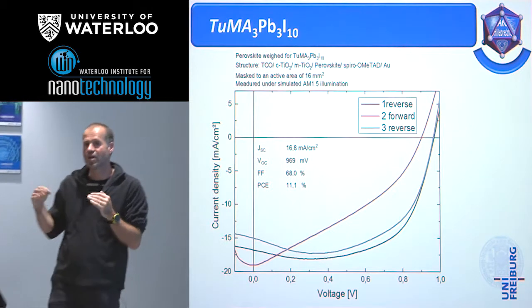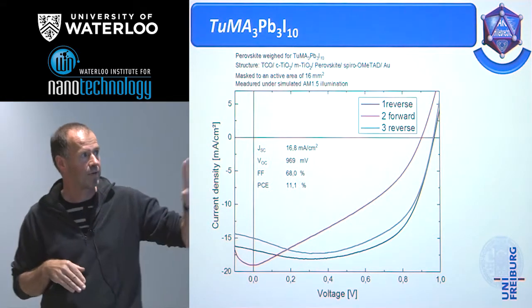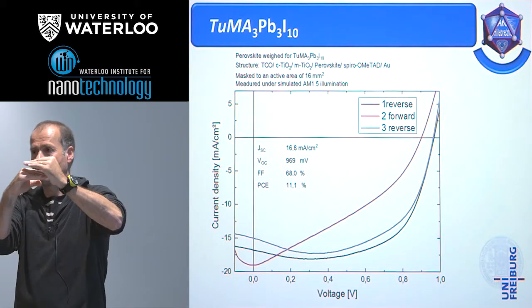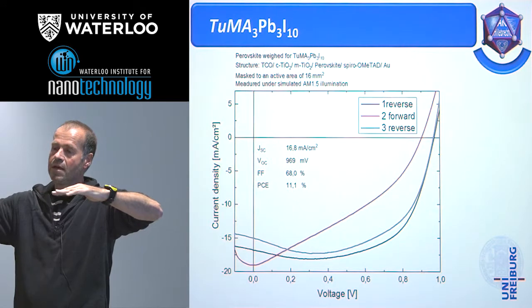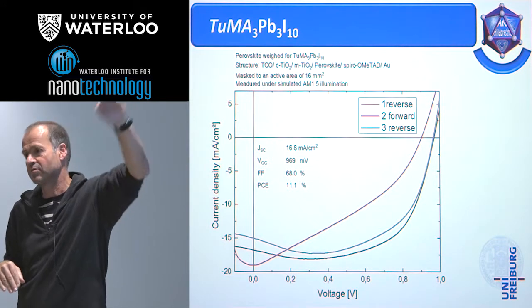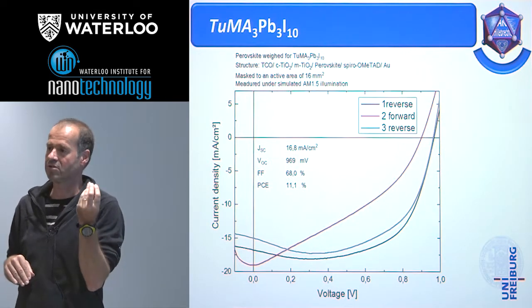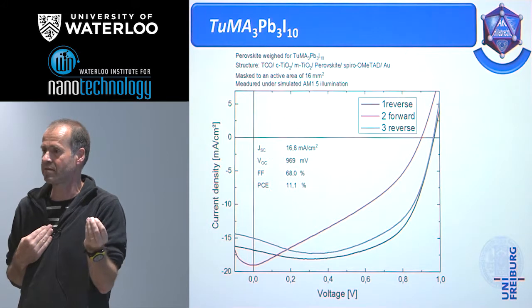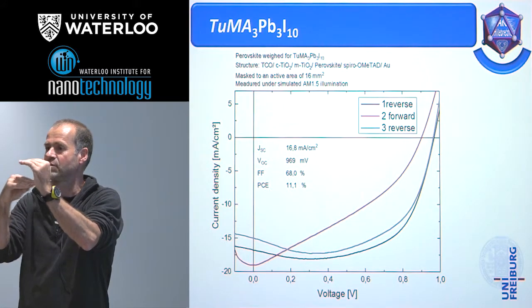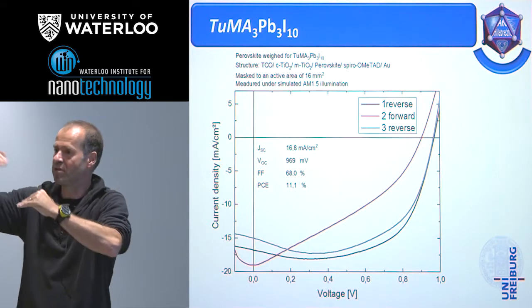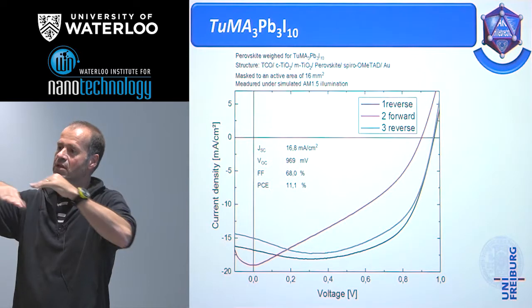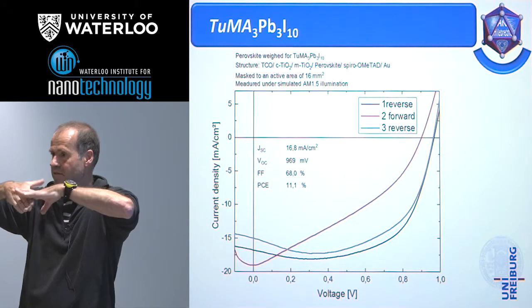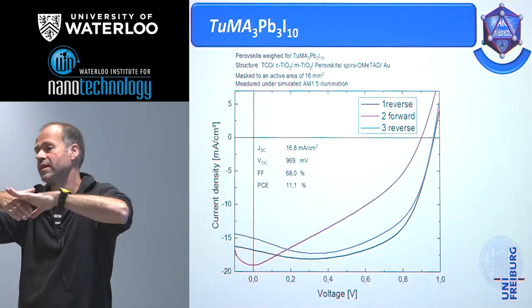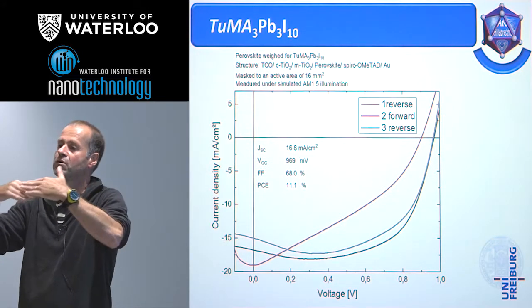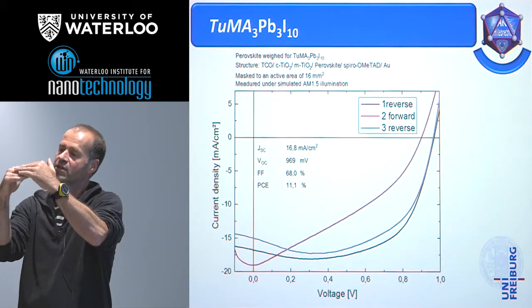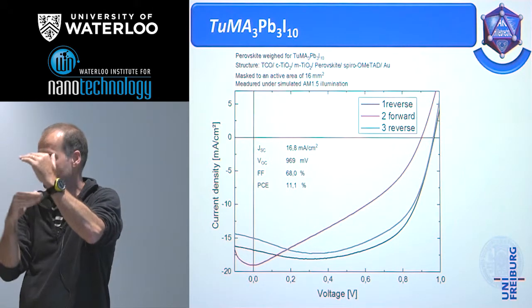It has an influence on the charge transfer. And I didn't comment on it too much, you have to precipitate the layer on the device. And two-dimensional perovskites are anisotropic within themselves, and you always need a charge transfer process. If you have a pure two-dimensional system, it's difficult to come over the gap between the layers. But depending on the microstructure, there's a conductivity between the different layers, and the contact is better the thicker the layer is. If you have a very thin layer, the probability of a broken contact between the layers increases. So obviously there should be a certain thickness of the layer.